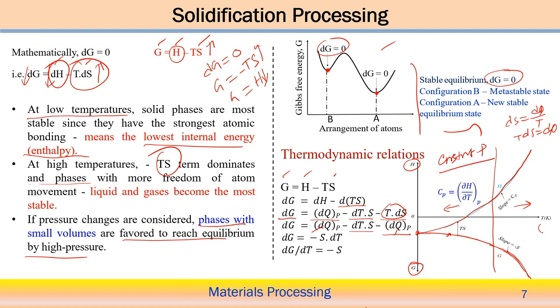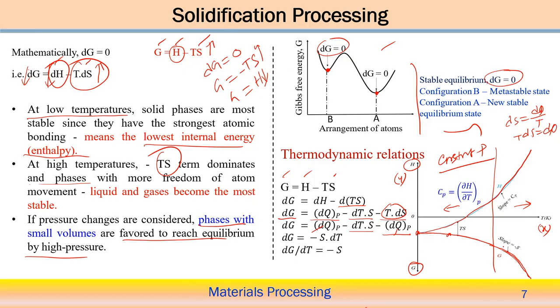So consider the slope of this curve, with G on the y axis and temperature T on the x axis. Here dG by dT represents the slope. So at any point the slope is equal to minus S. Here again the slope indicates minus S. Similarly, in the case of the enthalpy curve, H versus temperature T, dH by dT at constant pressure indicates the specific heat. We know that dH equals Cp into dT, where Cp is the specific heat at constant pressure. So the slope of the enthalpy curve represents the specific heat of the system.